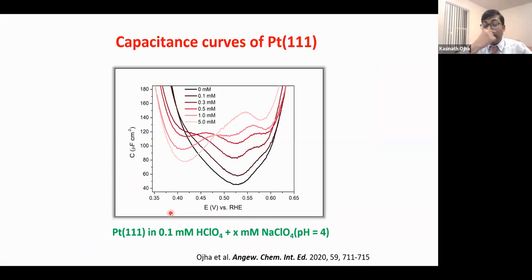Very strange. And then I went even much lower electrolyte concentration, like a micromolar concentration, 10 times lower. And probably in the world, nobody did measurements at that low electrolyte concentration. I went to 100 micromolar electrolyte concentration, and that time I see a minimum in the capacitance curve. And as I increase the ionic strength a little bit, my capacitance goes higher and higher. And at some point, I don't see that minimum anymore.